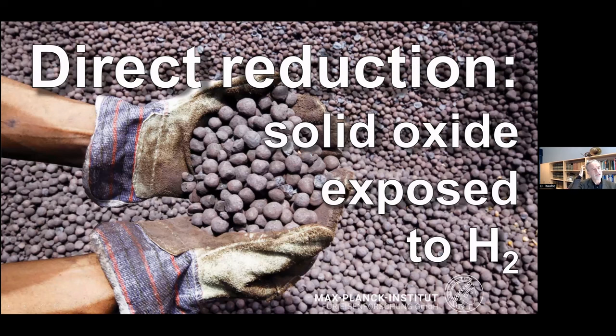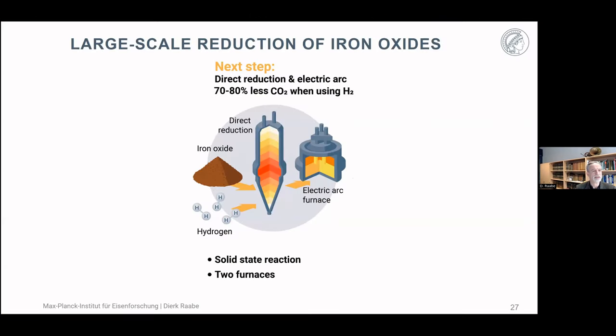So when we talk about the so-called direct reduction method, you take solid oxides, and the solid oxides on the market today are relatively pure. So we work mainly with relatively pure materials, also with high purity single crystals as reference materials, etc. But what you see here is a typical commercial pellet. That is a centimeter-big little sphere that is sintered, very fine dust-like iron oxide that comes typically in our country or in Europe from Brazil and from Australia. And you expose those solids to hydrogen. So that is what we are doing. And that is shown schematically here.